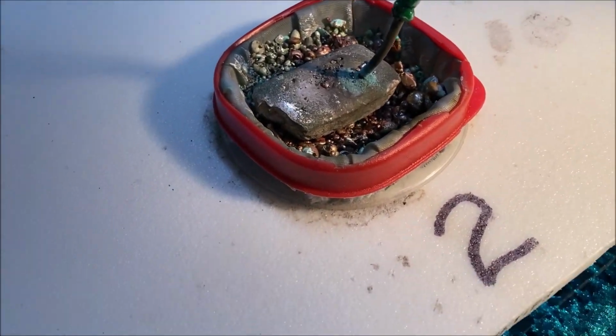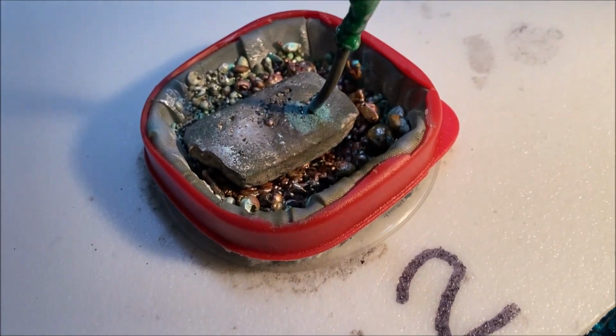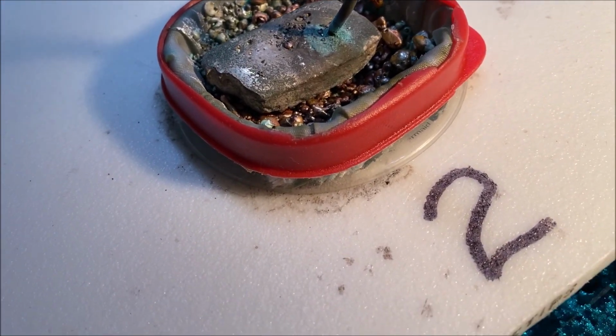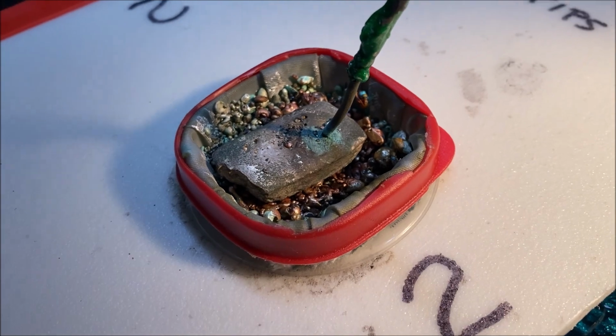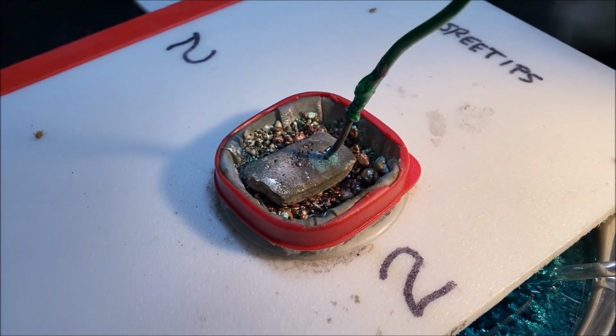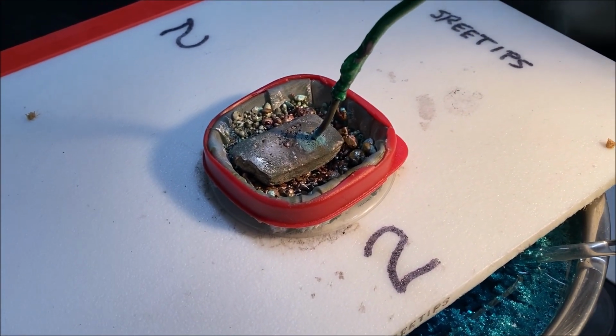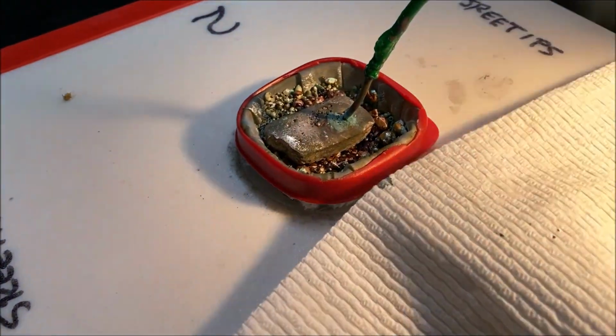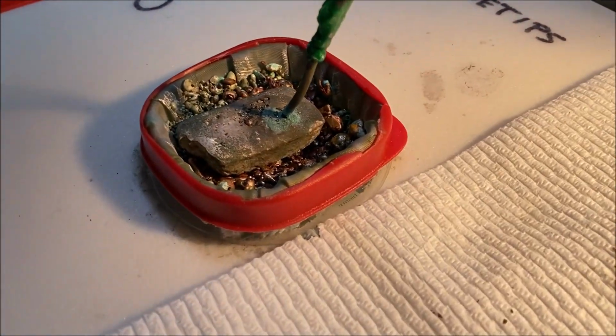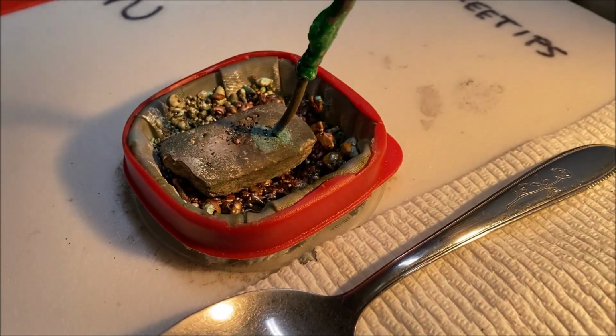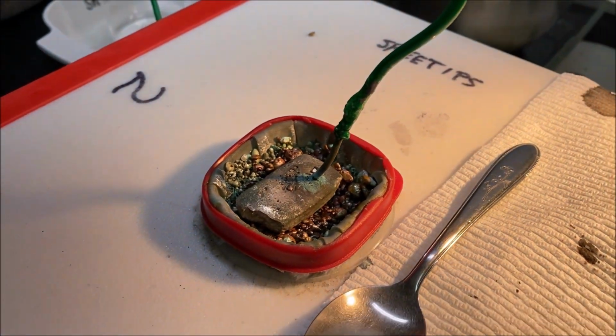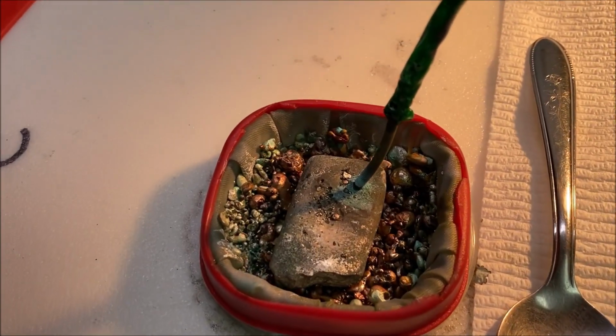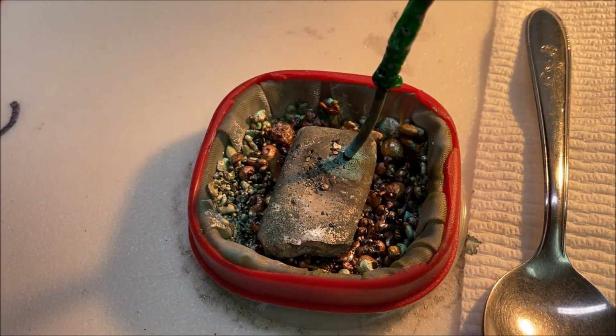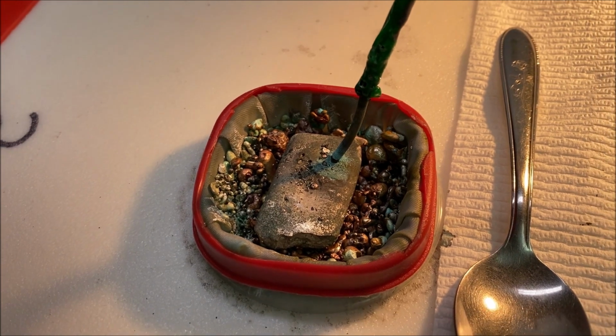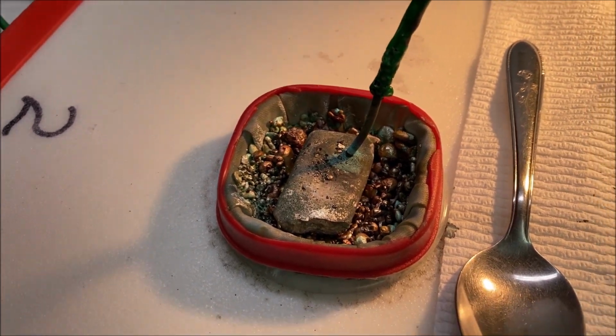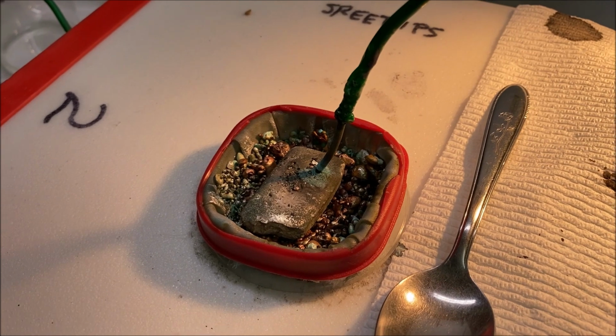The consumption of the silver up here in the anode basket has slowed way down, and I think that's because that second batch of shot that I had in that different container was a lot less clean, a lot dirtier than the previous batch of silver shot that I used. And so what we're doing is we're clogging up that anode filter and slowing the current flow down, and that will slow down the crystal growth.